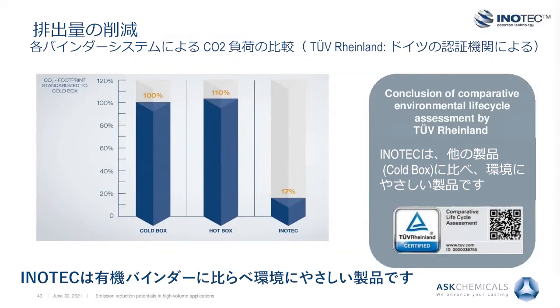The lack of dry ice usage in the cleaning process and the lack of energy consumption for the air treatment systems in case of INOTEC leads to a considerable decrease in the CO2 footprint for INOTEC. Conventional hot box binder systems based on organic components show an even higher CO2 footprint than cold box.